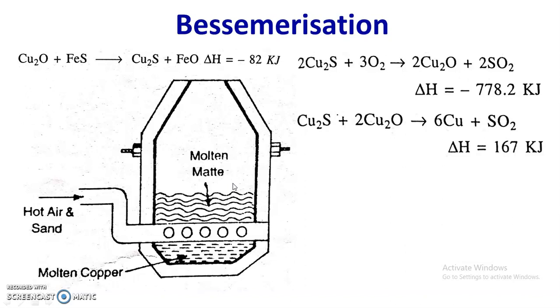As the copper solidifies, sulfur dioxide gas, which is formed as a byproduct, escapes from the reaction mixture, giving the copper an appearance like a blister, and therefore it is called blister copper. The product has a composition of 97 to 99% copper and 1 to 3% impurities of iron, nickel, arsenic, antimony, bismuth, silver, gold, platinum, etc.